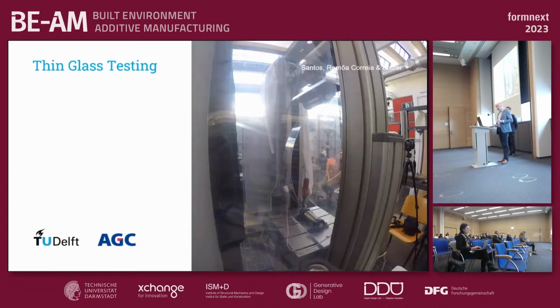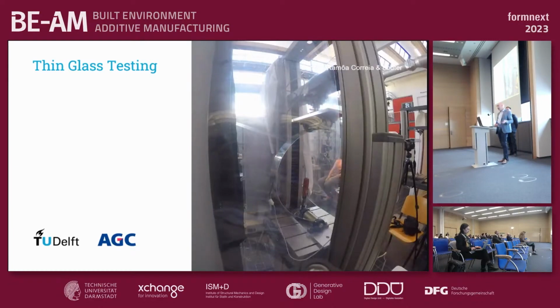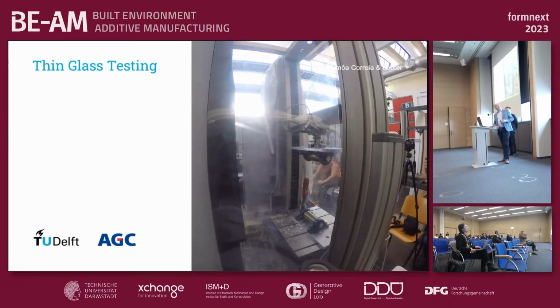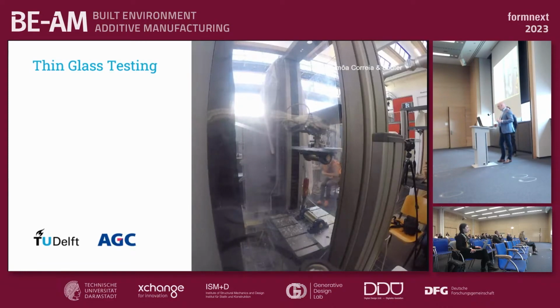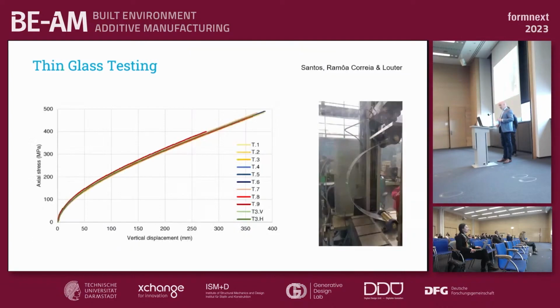Here you can see a small test on 2 millimeter glass, so actually in the thicker range, I would say. So we do some column buckling by pressing it downwards, and you can see the glass quite bending outwards. We have a strain gauge on there to measure the strain and calculate the stress from that, to see how far we can bend it before it fractures. And then it slows down the video, because we arrive at the full fracture. Just one disclaimer, it breaks quite explosively, because there's a lot of strain energy in the glass. If I would drop this piece of glass, it will fracture in big pieces, so a bit safer than this. But now we have so much built-up energy that once it breaks, it's exploding in all directions. So very strong thin glass.